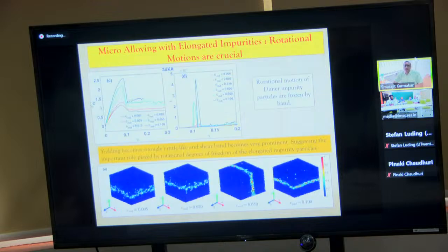So then, just for the sake of theoretical curiosity, what the student did was stop the rotational degrees of freedom of these dimers. So the dimers in the simulation can no longer rotate; they are frozen by hand. If you do that and look at the same stress-strain curve, we see that the stress-strain curve becomes very different. Now the yielding becomes extremely sharp, which is signaled by the susceptibility.